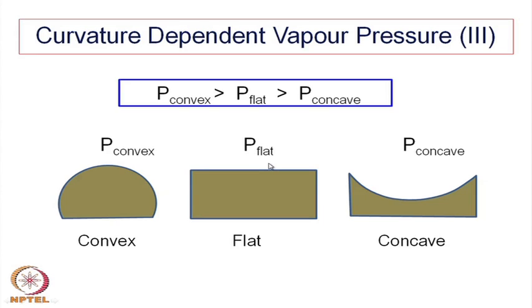Incidentally, you must know that whenever a material is kept anywhere in any environment, there is always an equilibrium. So, there will always be some vapor of that material; the solid will try to equilibrate with the gas phase, whatever the gas phase is. Of course, this equilibrium becomes faster kinetically when there is a high temperature and the evaporation rate is fast. If the evaporation rate is not fast, thermodynamically it has to be in equilibrium, but kinetically it may be a very sluggish or slow process.